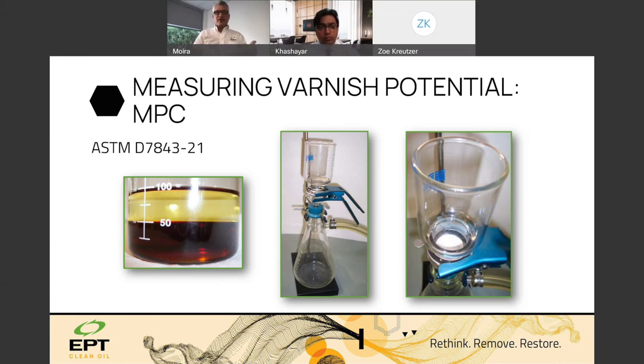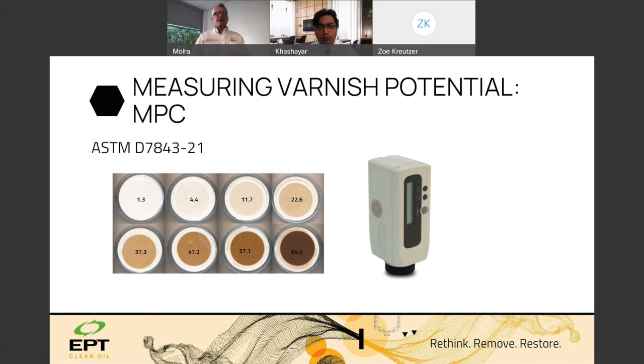The varnish test is very straightforward. You mix 50 milliliters of oil with 50 milliliters of solvent, and that solvent's purpose is to convert everything that's dissolved into that oil into a solid so that we can see it now, okay? If we didn't use the solvent, it would just be a patch test. But when we use the solvent, it allows it to be showing what that accumulated oxidation material is like. We get a patch, we get a color intensity on that patch. We use an instrument, a spectrophotometer, to measure the intensity of that patch. But what this is telling us is that the darker the stain on the patch, the higher the potential for my lubricant to form varnish.